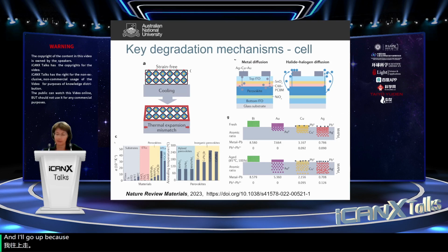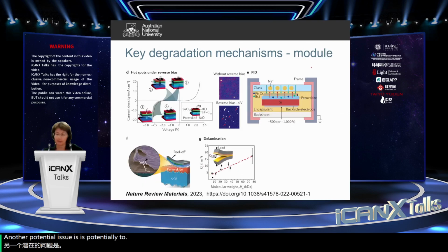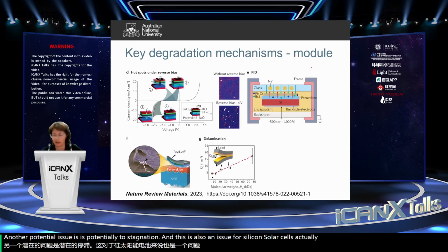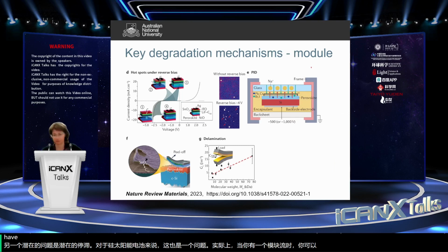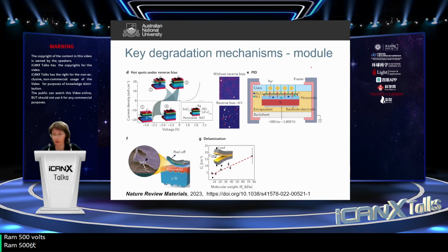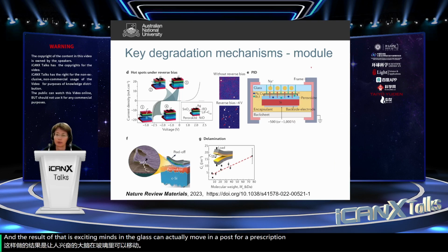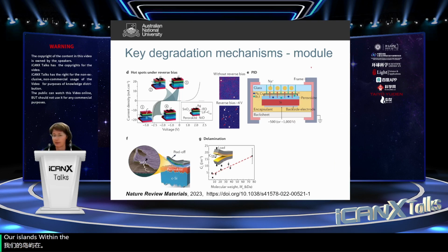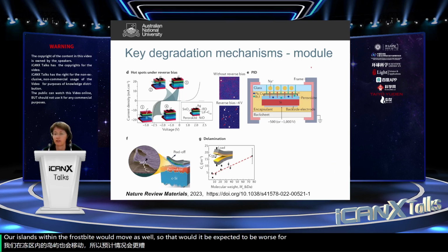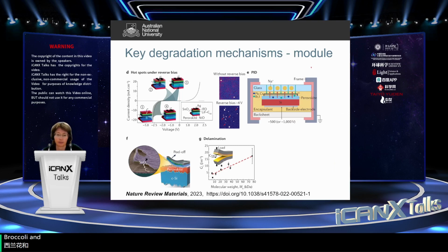Another potential issue is potential induced degradation. Now, this is also an issue for silicon solar cells, actually. When you have a string of modules, you can have around 500 volts between that module and the ground. And the result of that is that sodium ions in the glass can actually move. And of course, for a perovskite, ions within the perovskite could move as well. So that would be expected to be worse for perovskite tandem modules.